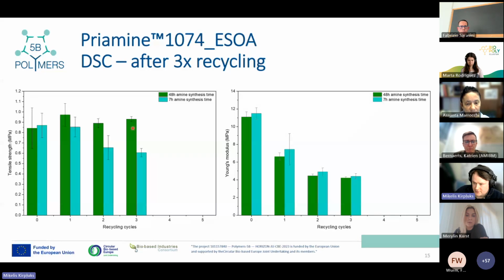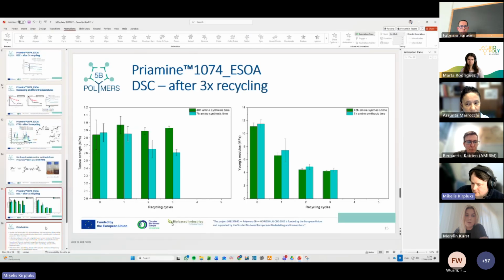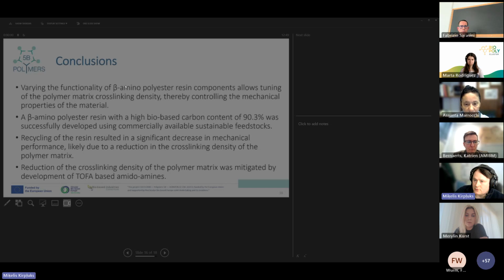At the moment, we're still optimizing the synthesis of these bio-based amines. We probably have not achieved full conversion in 7 hours because at 48 hours the material properties are better, and we still need to work on the explanation of what happens to Young's modulus after the recycling. But the tensile strength stays more or less the same after the recycling cycles and does not drop off. And to conclude,